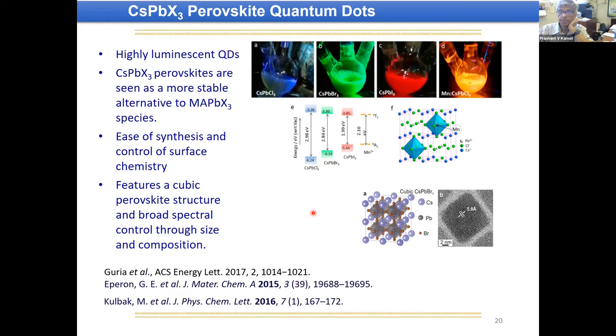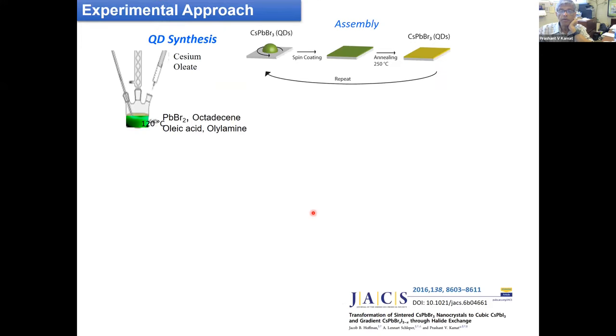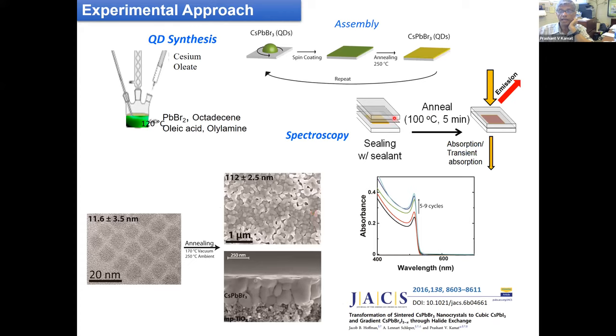So we make this synthesis, we spin coat it, and we can put it between two glass slides. Now it is ready for doing emission studies or transient absorption studies. And again, when you start with these colloids and anneal them, they grow in size from 11 nanometers to 112.